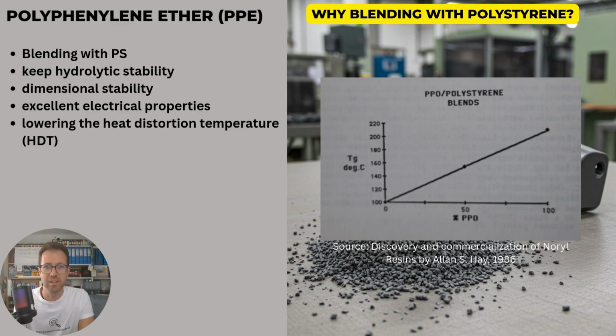And you can see here now on the right side, this is the original chart published by Mr. Alan Hay, where they show the PPO polystyrene blend and the change of the glass transition temperature. So on the left, when we have 100% polystyrene, we have 100 degrees C glass transition. So if we add now 50% PPO resin, we end up around 140 to 150 degrees C. And this is what we see now typically in these Noryl resins. And then, as mentioned before, on the upper end, we have the over 200 degrees C.